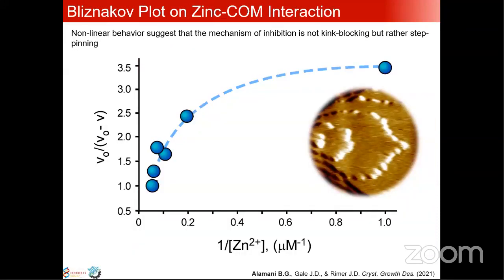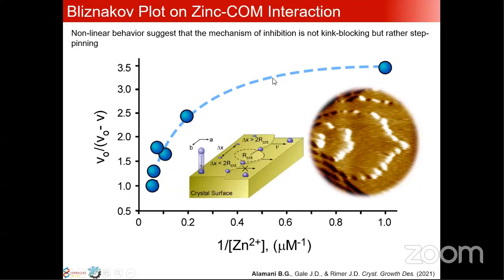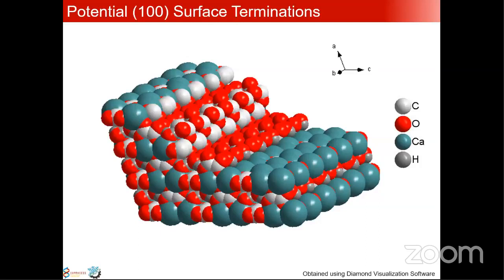Okay, so now what we did is we tried to identify how zinc inhibits or controls the growth of the crystal. Based on this model presented by Bliznakov, we found out that it most likely is step pinning. And as we recalled earlier, the characteristic of step pinning is the presence of corrugations on the step edges of a growing crystal that is influenced by the modifier. This is also another piece of information that we got, that possibly because of zinc, there are changes on the surface terminations. On these surface terminations, you might have calcium exposed, oxygen exposed, some hydrogen, and carbon is also exposed. So it depends. That is one thing, but this is still an ongoing study. We wanted to know what exactly those particular terminations are.